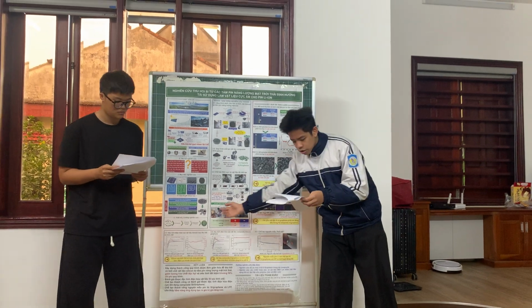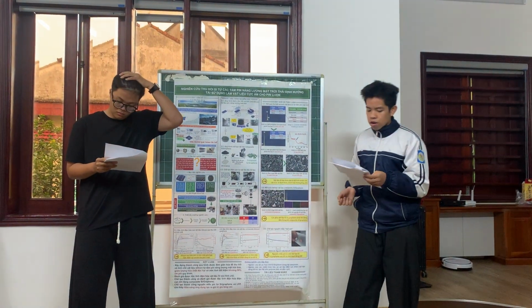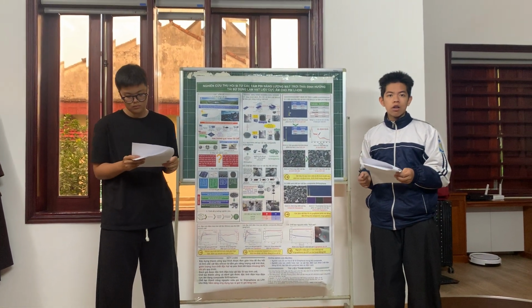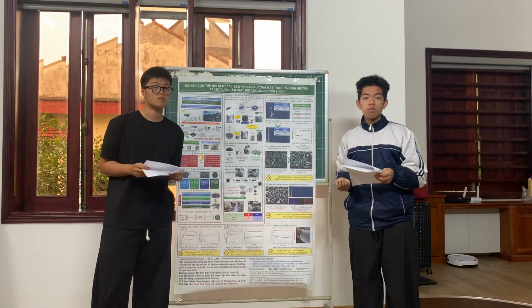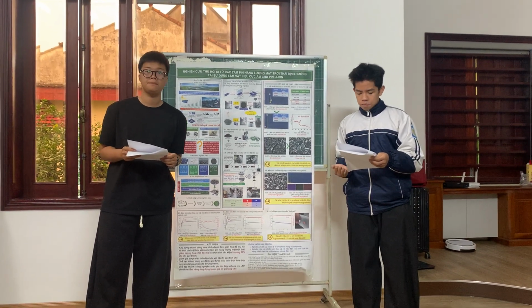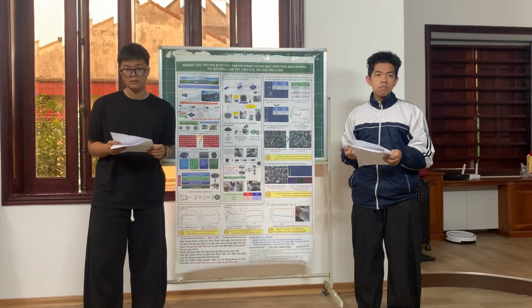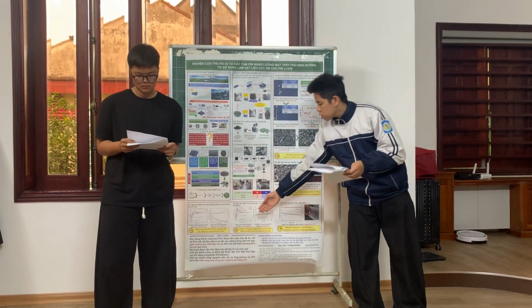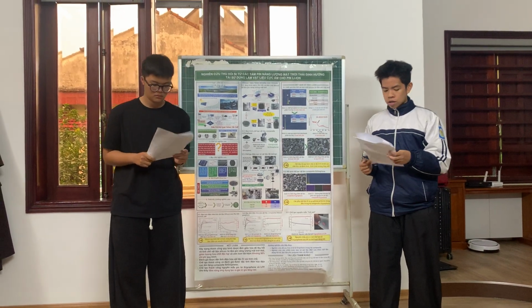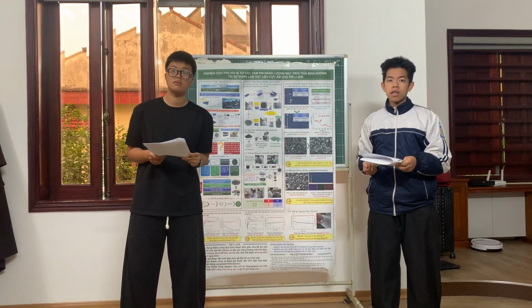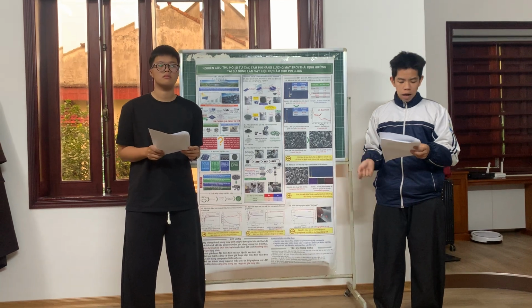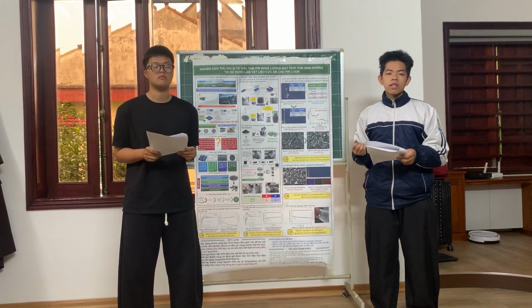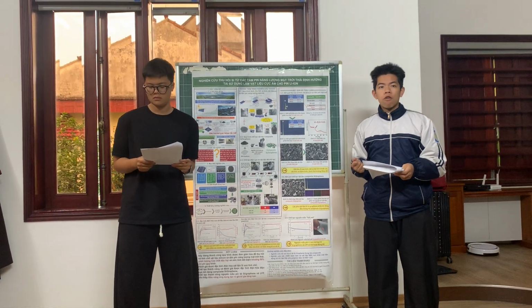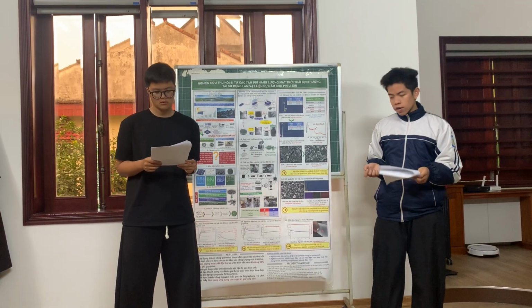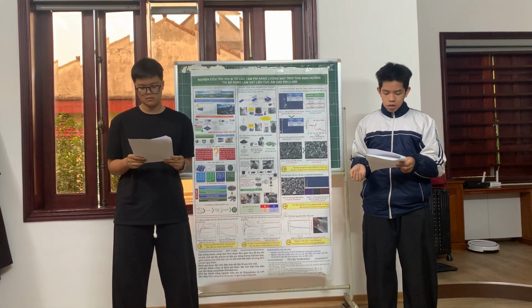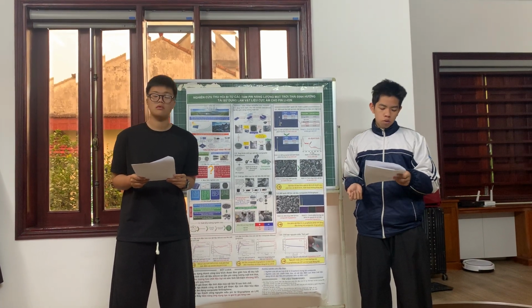The CV curves of raw silicon electrodes in figure 3.8 display distinct cathodic and anodic peaks, corresponding to reversible lithiation and delithiation processes, and demonstrating the rechargeability of the anode material. From the GCD result in figure 3.9, the initial capacity of silicon reaches approximately 1,600 mAh per gram. However, rapid capacity fading occurs and the electrode fails after about 50 cycles. This indicates that recovered silicon can be used as a lithium-ion battery anode. However, its cycling stability still remains limited.